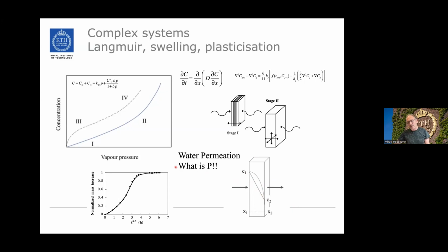However, when you have these plasticizing systems, it's not a linear slope that drives the diffusion. It can actually take extreme forms, very different from this linear one. So when you calculate the permeability of water in a system where water plasticizes it, you should not use the permeability P. You can call it specific water vapor transmission rate, for example.